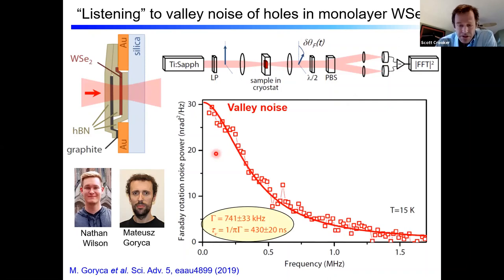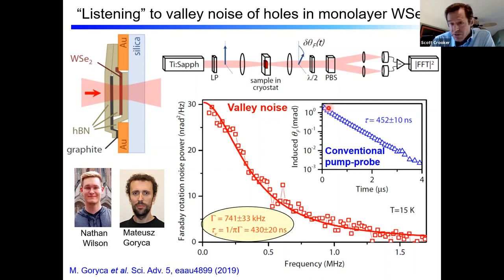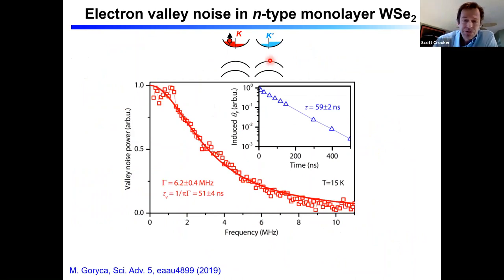So this is some of the raw data, the noise spectrum from, in this case, P-type doped, or holes. And you can see that the noise is peaked at zero frequency, and it's very narrow. The half width is less than 500 kilohertz. And what that corresponds to is a very long valley relaxation time, something like half a microsecond, which is encouragingly long, actually. Of course, we did confirm that with conventional pump probe measurements, and the two values agree very well, about 450 nanoseconds. We can do the same thing in exactly the same sample just by changing the gates.